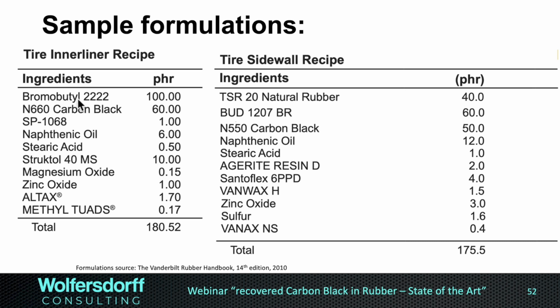So inner liner, we have butyl, we have halogenated because the halogen atoms are very big, and this adds to the airtightness of the inner liner to prevent flat tires. Sidewall is different. We have natural rubber, we have a little bit of BR rubber. In one case we got N660 carbon black, and the other case we got N550 carbon black. The PHR is per 100 resin. So if the resin is 100%, we need to multiply by the PHR of the additive we put on top of the resin. And I think this gives a nice idea for inner liner and sidewall recipes.